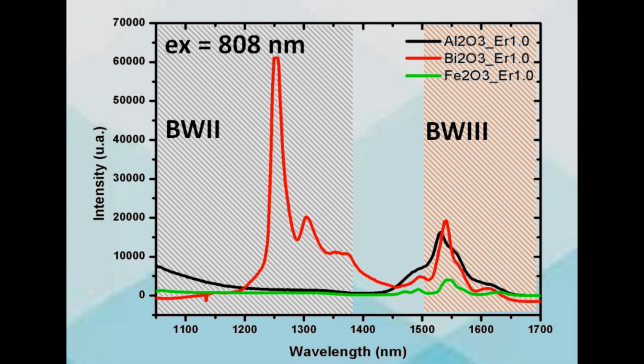The erbium-doped aluminum oxide shows a good photoluminescent response at 1550 nanometers when it is excited with 808 nanometers by the transition 4I13/2 to 4I15/2. For its part, the doped iron oxide sample has a lower luminescent response associated with the low absorption of the ion in the region of 808 nanometers. In the same way, the sample with the highest photoluminescent response at 1550 nanometers is the bismuth oxide doped with 1% of erbium, which also presents an emission centered at 1250 nanometers, typical of the matrix.